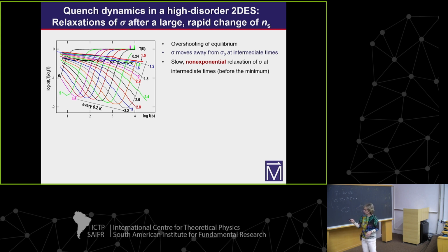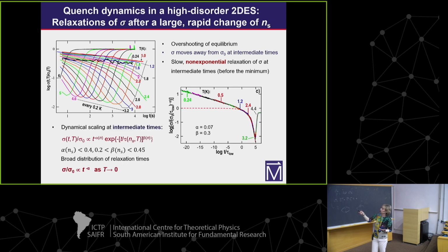So it turns out that all of these curves, first we want to see what happens before this minimum, before it starts going back up. And it turns out that all of these curves can be collapsed onto the same curve, which can be described as a product of a power law and a stretched exponential function.